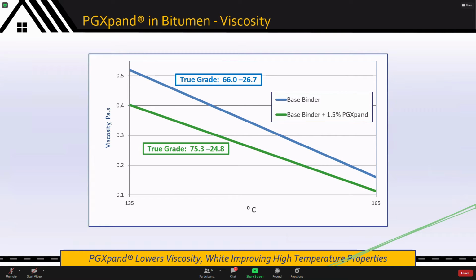Here is the viscosity versus temperature curve of a PGXpand sample. The blue curve is the viscosity of the base binder as a function of temperature, and the green curve is the viscosity of the PGXpand modified. While it is improving the high temperature properties, you can see across the entire compaction and production temperature span a 5 to 15% reduction in bitumen viscosity. So while it's improving the properties, it is becoming more user-friendly.